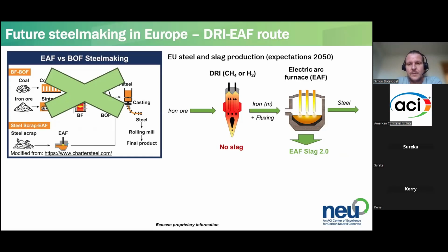Why is that interesting? As I said, in Europe, we regard the blast furnace, basic oxygen furnace route as the major steel making, but because of its CO2 emissions associated with the use of coal, for example, most European steel producers have announced to fade out or at least reduce production via that route, and replace it by a direct reduction reactor, which is a solid gas reaction, which will not produce a slag, and then remelting the iron and producing the steel in an electric arc furnace.